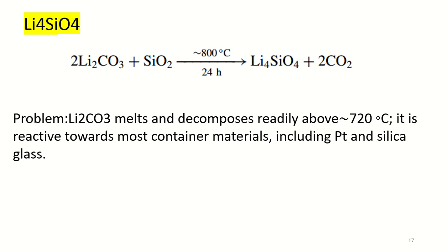So the problem is that lithium carbonate usually melts and decomposes readily above 720 degrees Celsius. It is reactive towards most container materials, even including platinum and silica glass. So what would be the solution for lithium carbonate, Li2CO3?